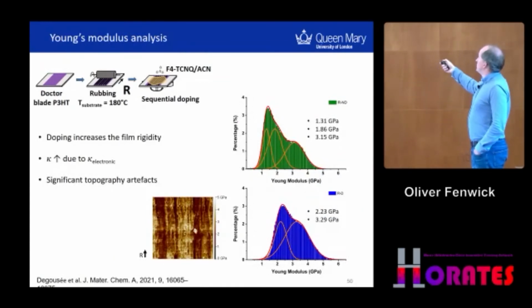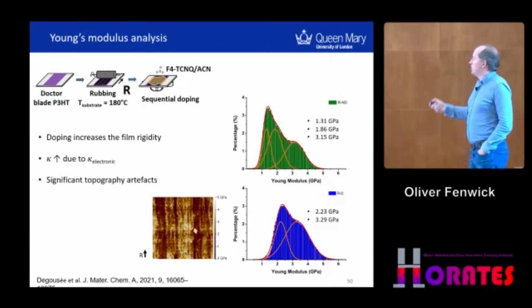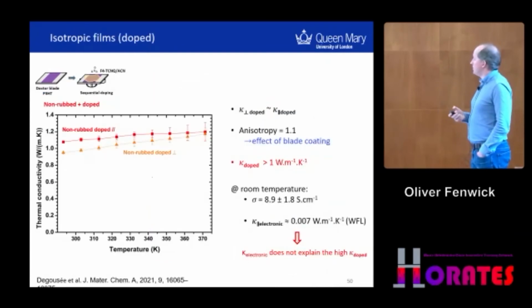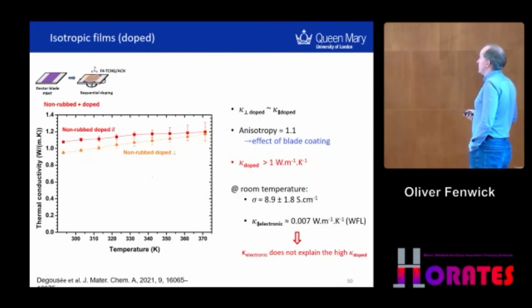When we dope, we see the disappearance of the components of the material that has a Young's modulus of around 1.3. When we dope it, that has gone. So it looks like we are increasing the stiffness of our film. The topography is very much the same as in the undoped case. The film is getting stiffer as well, and that might be driving the higher thermal conductivity.